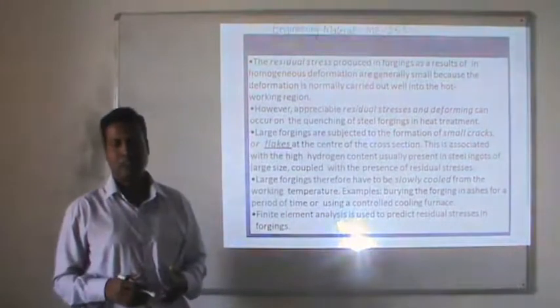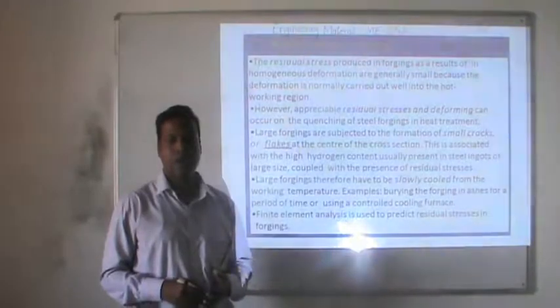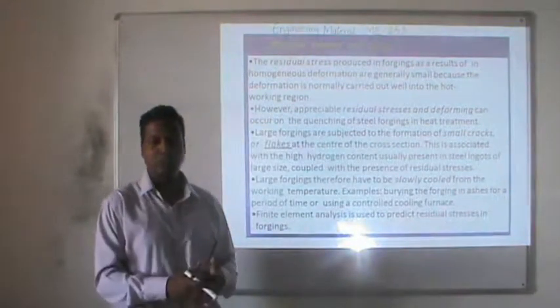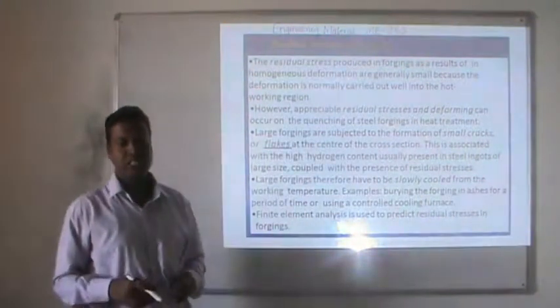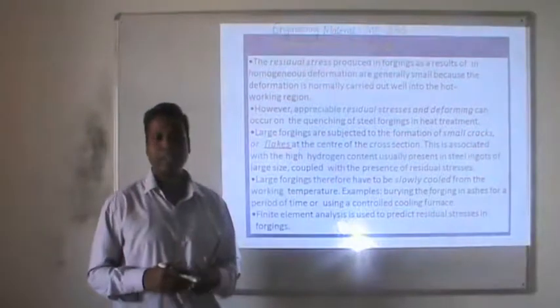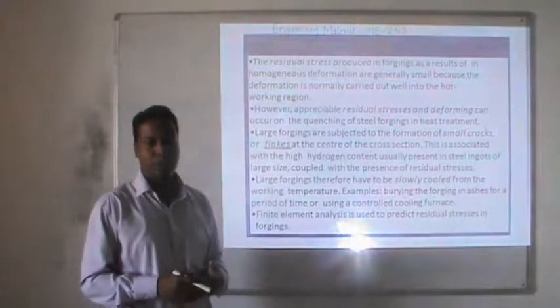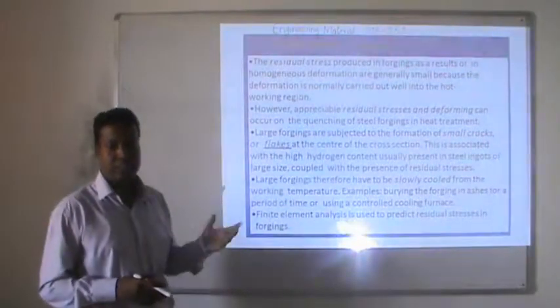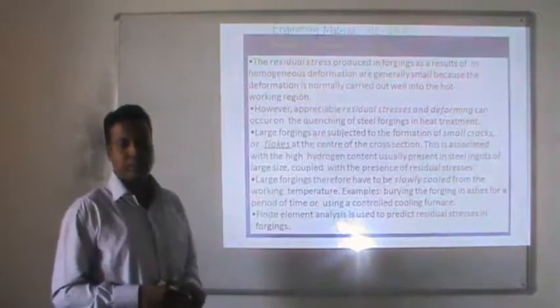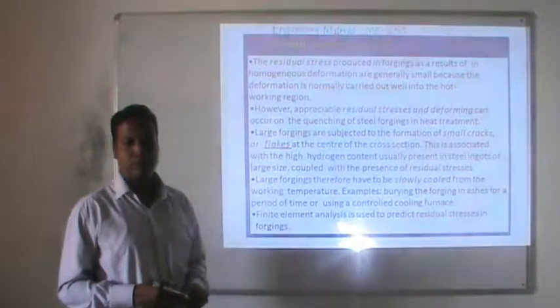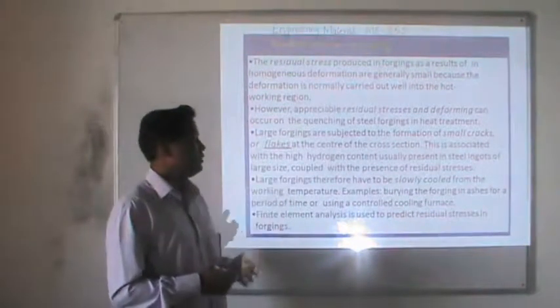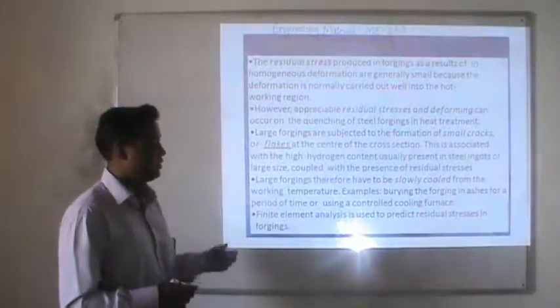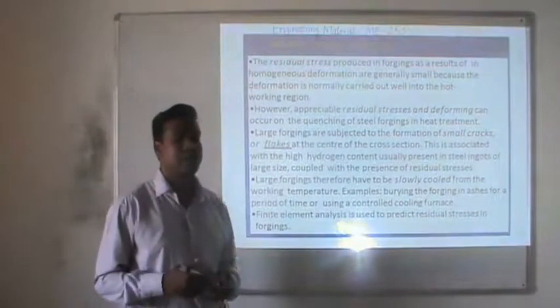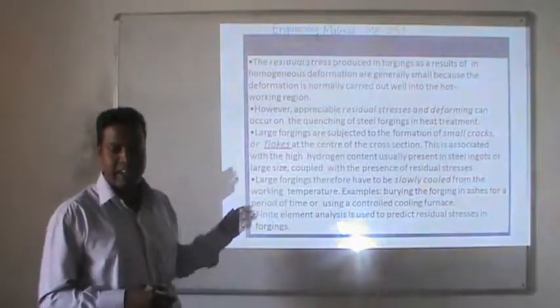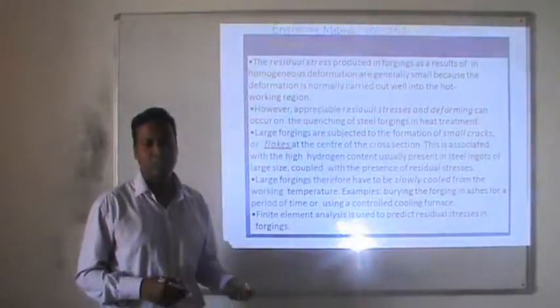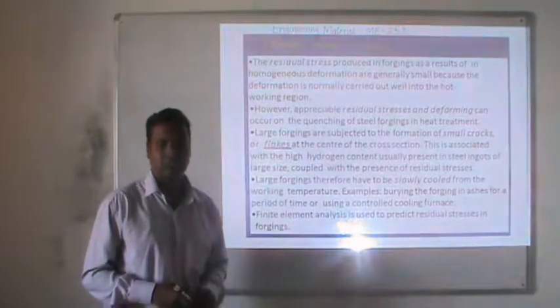Large forgings are subject to the formation of small cracks or flakes at the center of the cross section. This is associated with the high hydrogen content usually present in steel ingots of large size, coupled with the presence of residual stresses. Large forgings therefore have to be slowly cooled from the work temperature, for example, by holding the forging in ash for a period of time or using a controlled cooling furnace. Finite element analysis is used to predict the residual stresses in forging, as we discussed in the previous class.